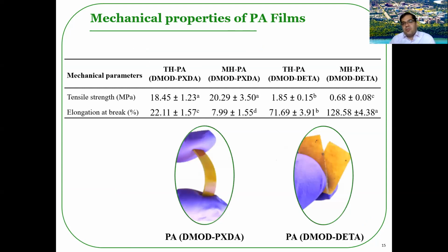The mechanical properties of the polyamide films were investigated using a universal testing machine. As you can see in this picture, the semi-aromatic polyamides DMOD-PXDA show the characteristics of a brittle thermoplastic polymer, while the linear polyamide DMOD-DETA illustrated the characteristics of a rubbery and very flexible polymer. Regarding the semi-aromatic polyamides DMOD-PXDA, different heating methods didn't have any significant effects on the tensile strengths of those polyamides, which was around 19 megapascal.